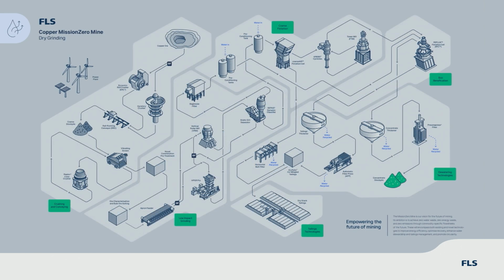Pretty much the same for the dry grinding. The only difference is that we were looking at HPGR finish grinding here. So that's using an HPGR fully dry with a dynamic static classifier, because we were trying to produce two products, which hadn't been done before. So we're producing the grits from the static classifier and the fines from the dynamic classifier. And we were able to do this, although we had to adjust our grind size to be 250 and 100 for this particular flow sheet.